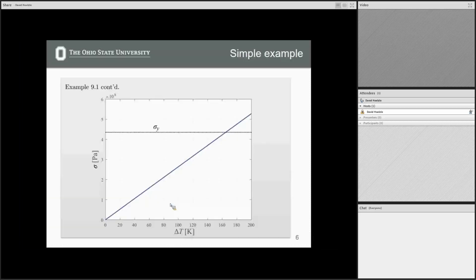So we can plot this. So here would be showing a linear change in the stress. We said that this is the range we care about. We're saying this model is approximately valid for temperatures such that the stress is below the yield stress. Above this, other things that are more complicated are going to happen. But we can see somewhere in the order of 170, maybe a little over 160 degrees centigrade or Kelvin, we get material that goes above the yield stress.